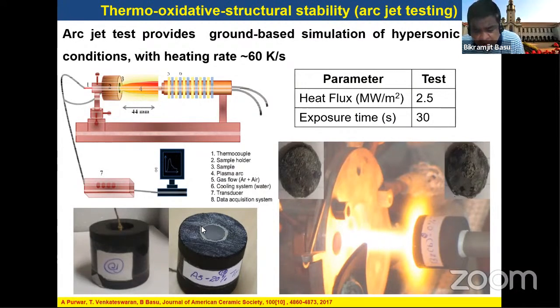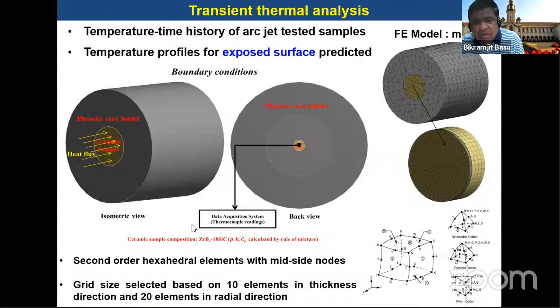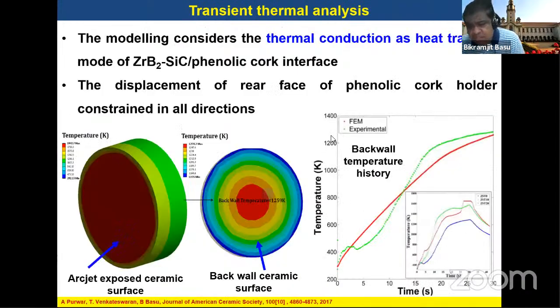And then we have done some computational analysis to find out the back wall temperature. By putting a thermocouple at the back wall, we can extrapolate what could be the front wall temperature which is exposed to this arc jet. This is how the temperature-time history looks from the finite element analysis, and you can see that the front wall temperature can be as high as around 1200 Kelvin. So essentially our UHTC is exposed to this kind of temperature and aggressive heat flux conditions during the arc jet testing.